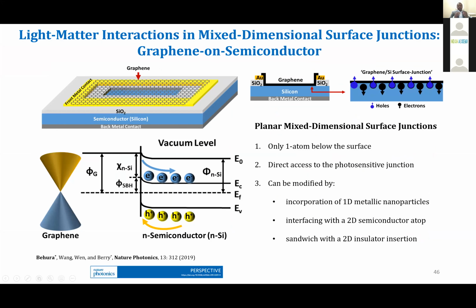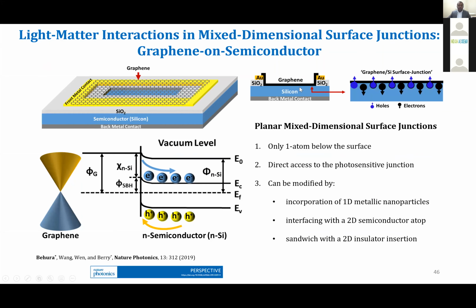And how 2D materials, these atomically thin materials, can be useful for photovoltaics has been our interest. We have done a little amount of work, and a lot of work is still going on and yet to be done. Here are some of the examples where we replaced one silicon. For example, in a silicon solar cell, you have a p-type and n-type, and you can replace either n-type or p-type with a 2D material, for example, in this case graphene, and then you will have a 2D, 3D kind of junction. And here the built-in potential or the junction actually comes very close to the surface.